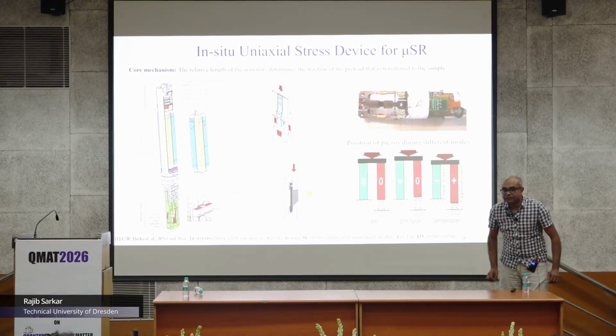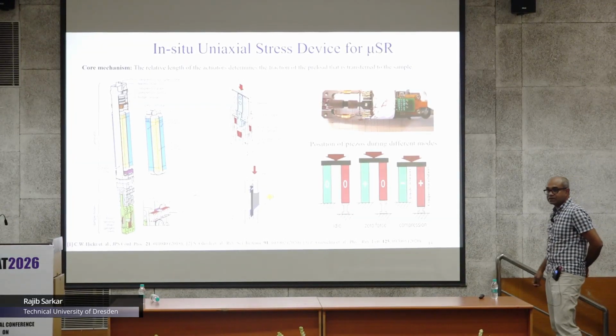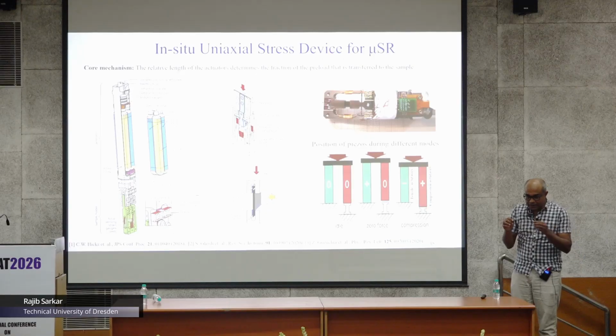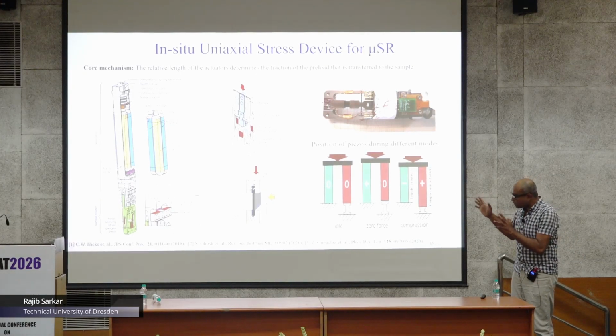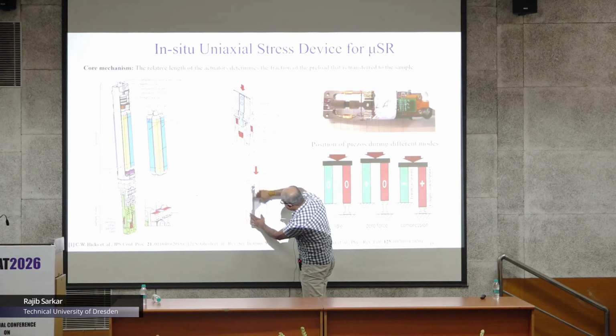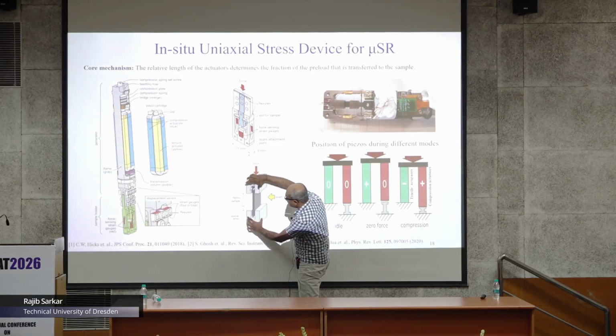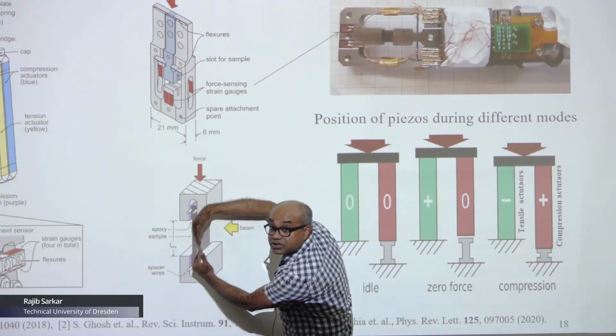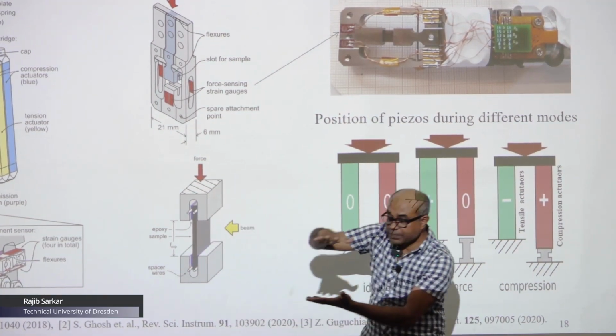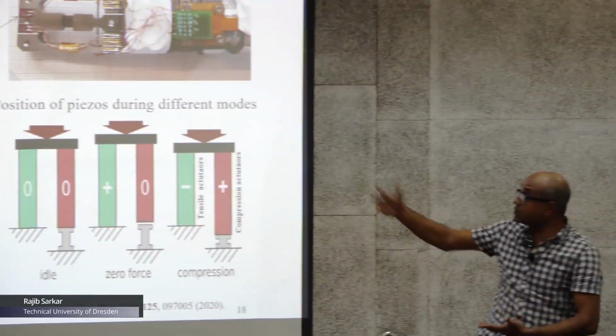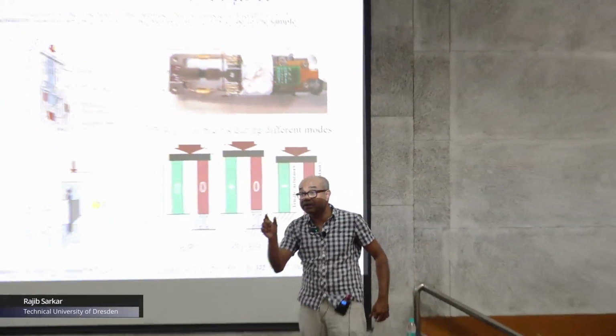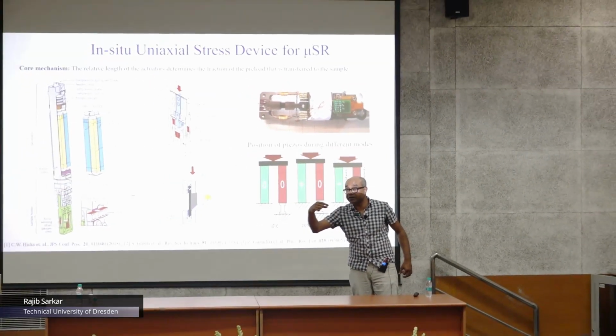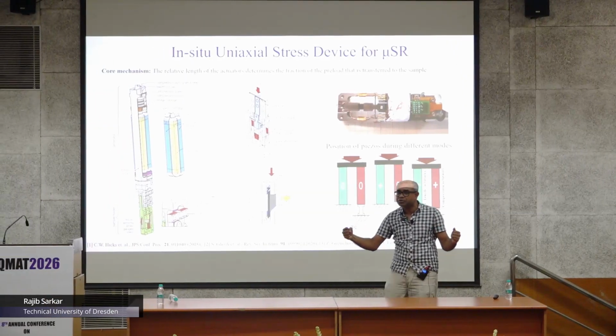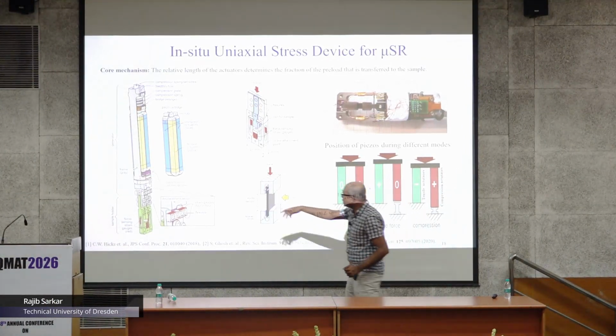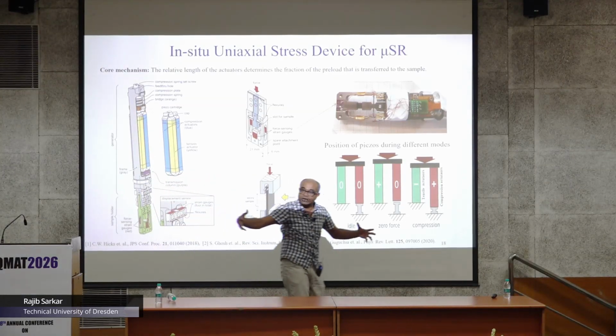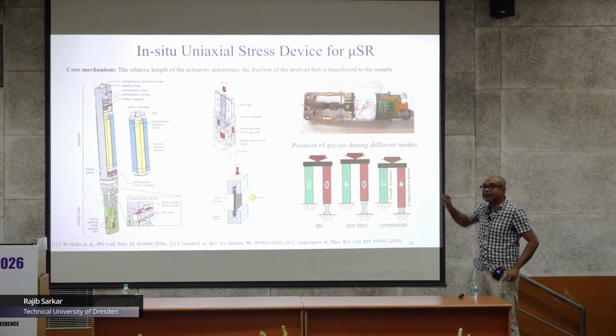The problem with the diamond anvil cell is that making a uniaxial pressure is rather challenging. Of course you can go to very high pressure, but if you really have to do uniaxial pressure, for example for this configuration, this is my sample, placed here. This is one direction, the 110 plane. We apply the force with piezo stacks, but the challenge is that you have a sample 5 to 6 millimeters long, 4 millimeters wide and 0.5 millimeters thick. Imagine you need 1000 Newton to apply it, and this is very difficult. Therefore you need a big configuration, with 4 large piezos, and then you can change the voltages and play around with these.